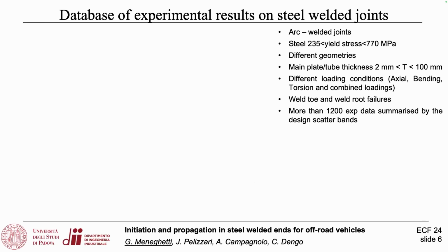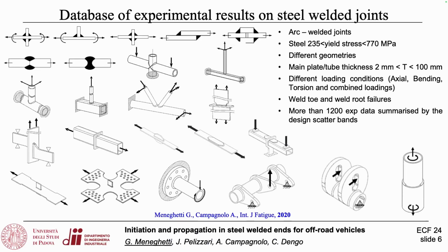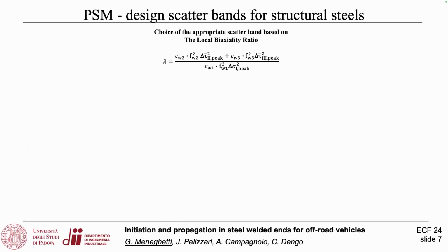We need the resistance curve to be coupled with the design stress. In the past, meaning in the last 20 years, we have post-processed more than 1,000 experimental data. We represented the data in terms of equivalent peak stress, and we came up with two fatigue design curves based on the local biaxiality ratio.